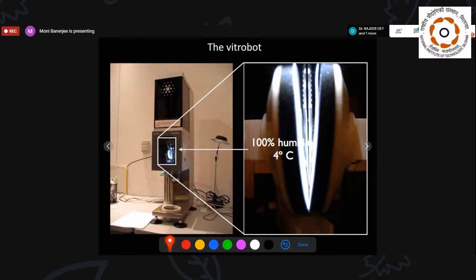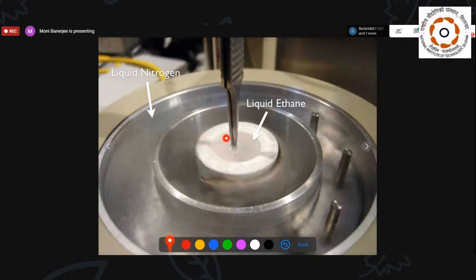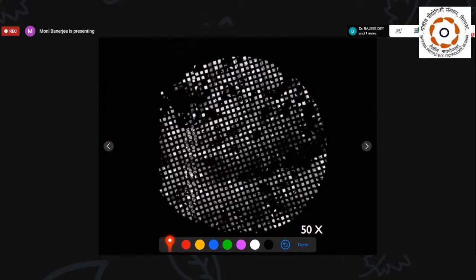We have a robotic device called a Vitrobot in our laboratory, where at a certain humidity and certain conditions of temperature, the sample is very, very quickly plunged into liquid ethane, which is being surrounded and cooled by liquid nitrogen. From this point on, the sample has to be kept at very low temperature. It has to be minus 180, because if the amorphous ice devitrifies and then reforms, then you get crystalline ice, and that will damage the sample, or the sample would not be imaged properly. Now, this grid is put in the cryo-electron microscope. It is being cooled continuously because the holder that holds the sample has a liquid nitrogen reservoir attached at the end. And as the sample is put in, now we start magnifying the grid and looking at what is there.